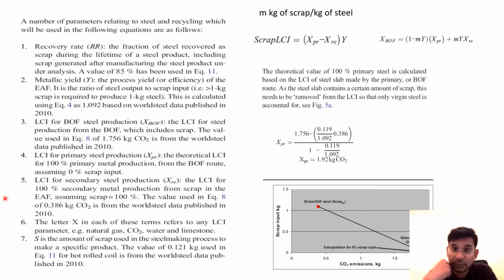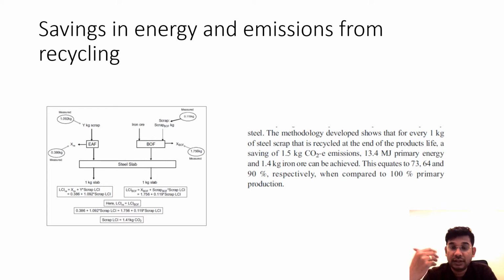So they tried to solve it with multiple different equations, and they tried to come up with the scrap life cycle inventory, and all these terms you could read through. This is something that you already know. So they found that for the primary production, when you have zero scrap input, you emit 1.92 kilogram of carbon dioxide per kilogram of steel. Okay, and then they finally found out that you save 1.5 kilogram of CO2 emissions, because the other thing is already measured, with 13.4 megajoules of primary energy that you save, which translates into 73, 64, and 90% of savings in emissions, energy, as well as in the reduction of ore use when you compare it with 100% primary production.